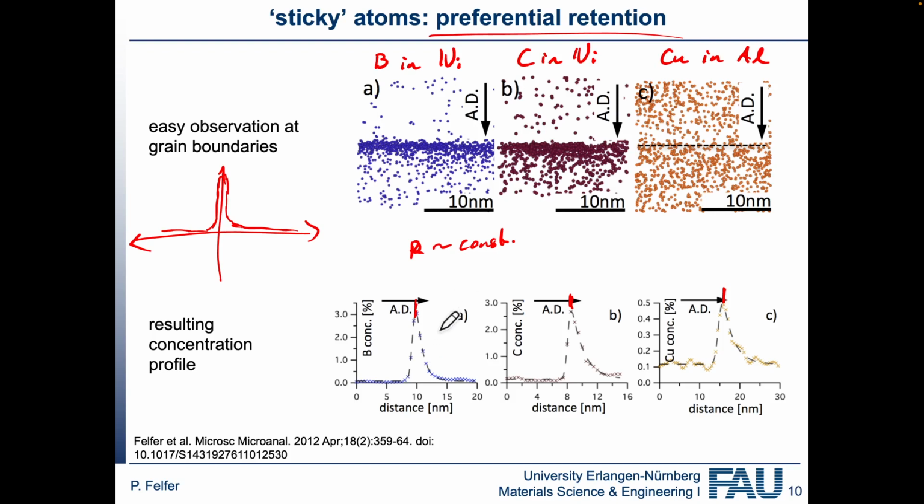And we can then go and derive a decay constant. If decay is very prominent, we can derive a decay constant for each element at a certain measurement condition in a certain host material. And we could then also use a deconvolution, for example, to get rid of that artifact, but then obviously you need to know a lot about how that actually works and if it's constant. And I don't think anybody has put enough effort into any kind of system to be able to do that confidently.